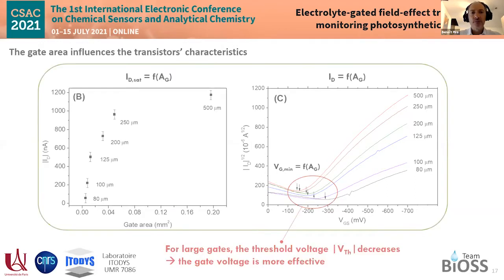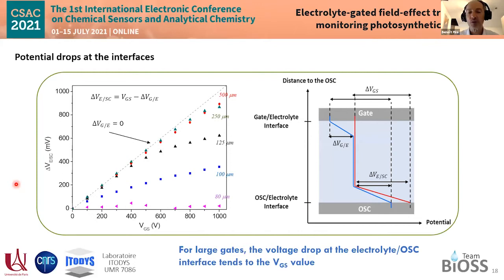I can continue with that. If we follow with a reference electrode, typically dipping in the electrolyte, if we try to follow the voltages at each interface compared to that of the reference electrode, of course, we could see that for large gate, the potential drop at the interface between the semiconductor and the electrolyte follows largely that of the gate.